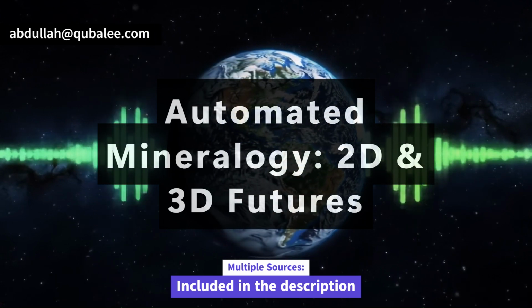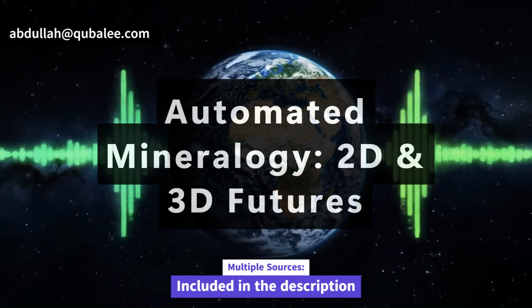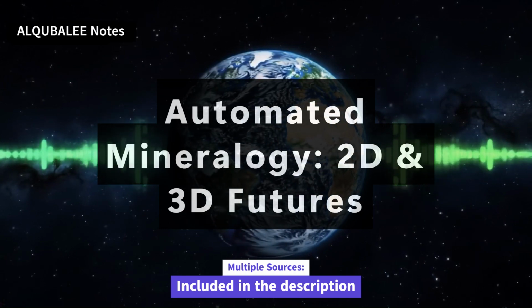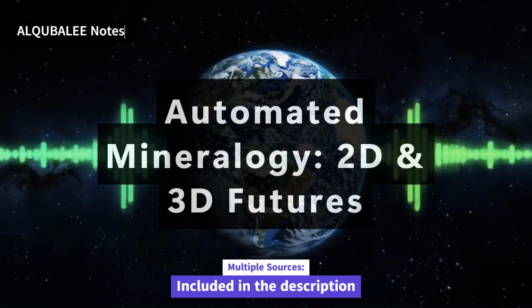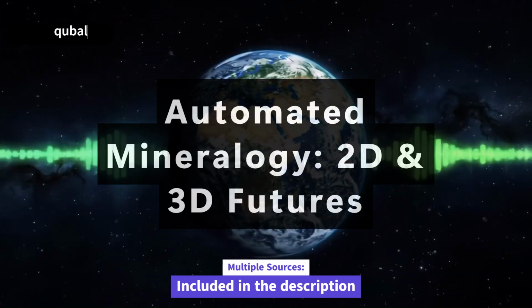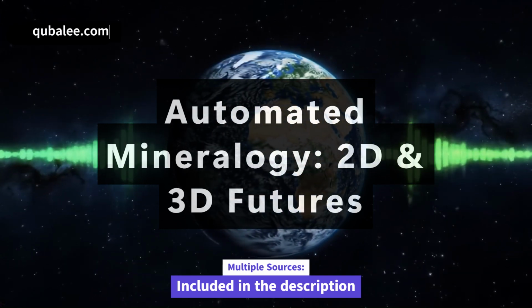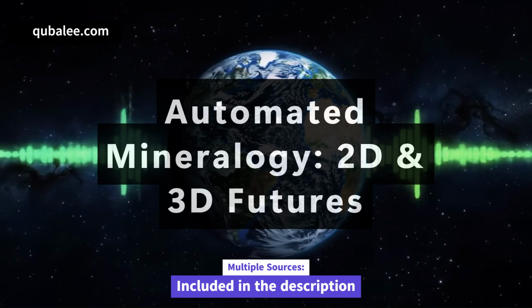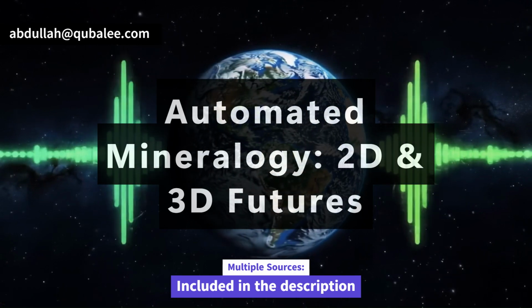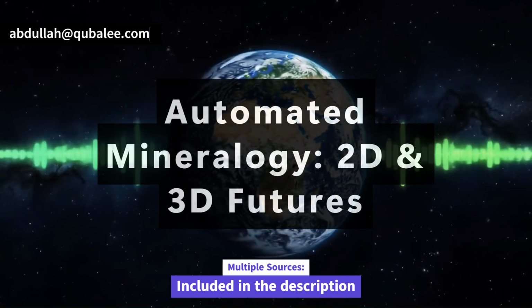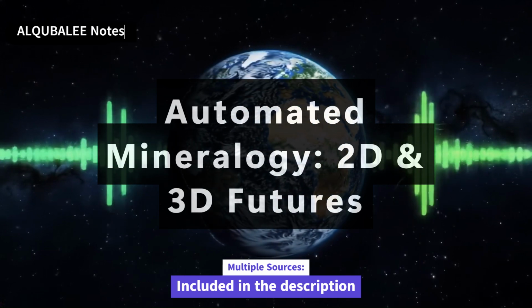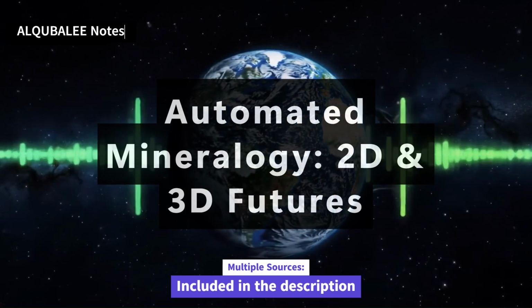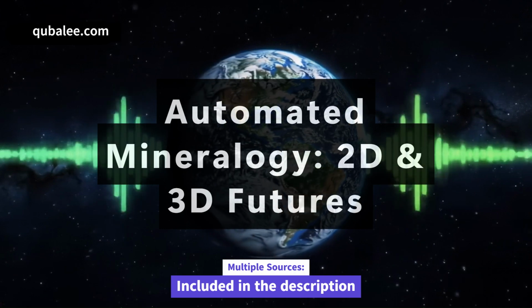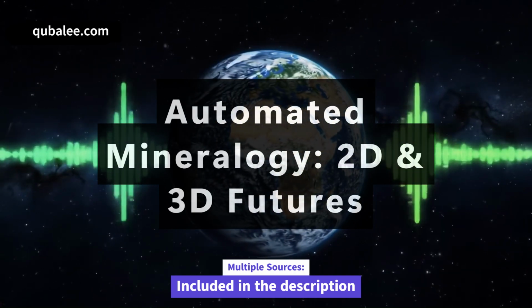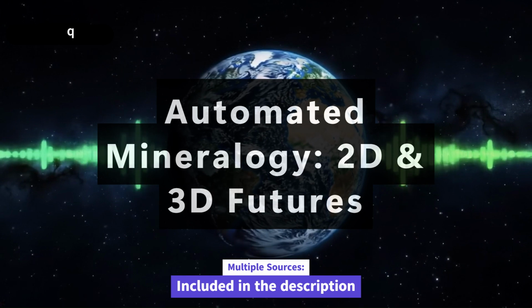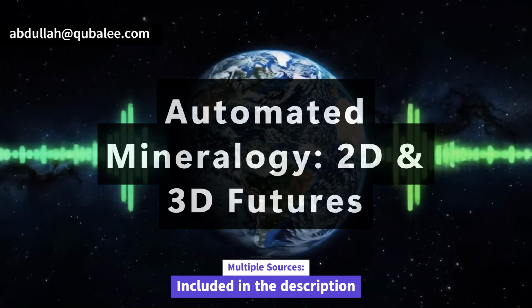That makes sense. And I thought this was interesting. It doesn't just rely on matching the shape of the spectrum, right? It can use the actual measured chemistry, too. Yes, that's another layer of sophistication. It can classify minerals using the measured percent mass fraction values of the elements calculated from the spectrum at that pixel. How does that help? It gives you deeper chemical insight right alongside the mineral ID. It directly links the specific quantitative chemistry measured at that spot to the mineral classification, rather than just relying on a general spectral pattern match.